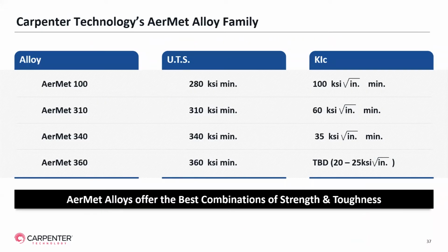And to go more specifically into the strength and the toughness of each alloy, AirMet 100 has the 280 UTS, nice strength, nice toughness. AirMet 310 kicks it up a notch. Of course, as you can see, as we kick it up a notch, the toughness goes down. Right now, we're working on the AirMet 360. It's got nice 360 KSI strength. We're working on the toughness. Right now, it looks to be in the 20 to 25 range, but we're trying to optimize that as best as possible.